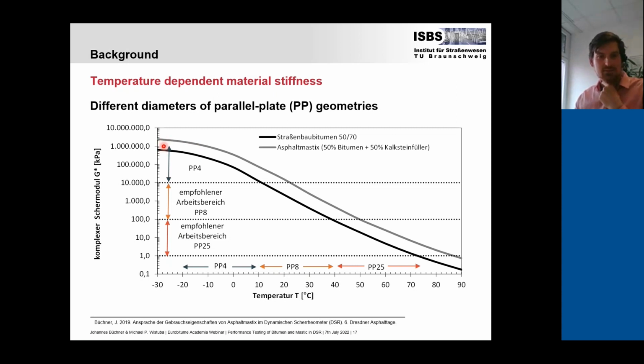It's actually 6 times more stiff compared to the bitumen, but still almost the same behavior. Now, when looking into the standards and the recommendations, there are, depending on the stiffness and the shear modulus, recommendations which geometries to use in the DSR. So basically, the parallel plate geometry is used, and the recommended range for 25 millimeters here is 1 kilopascal to 100 kilopascal. Then from 100 kilopascal to 10 megapascal, it's the 8 millimeter geometry, 8 millimeter in diameter.